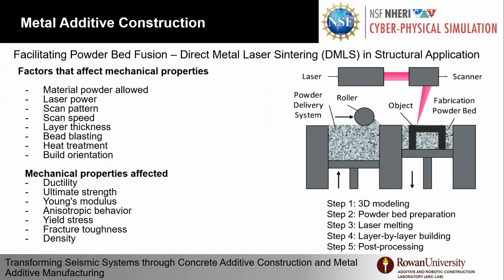Here are the factors that could affect mechanical properties. For sure, the powder used: we can use stainless steel powder, titanium powder, or nickel. The laser power, the scanning pattern, scanning speed, layer thickness, bead blasting, and heat treatment. These also have an impact on ductility, ultimate strength, modulus of elasticity, yield stress, anisotropic behavior, and fracture toughness.